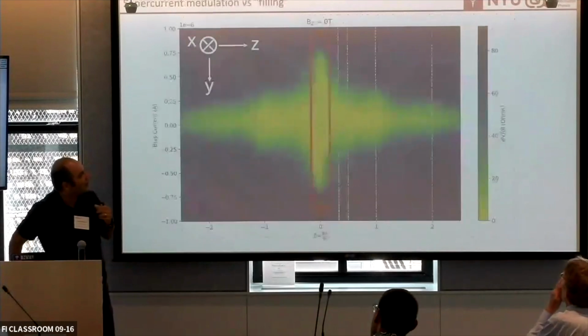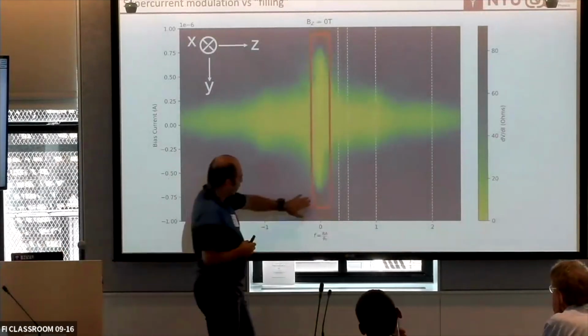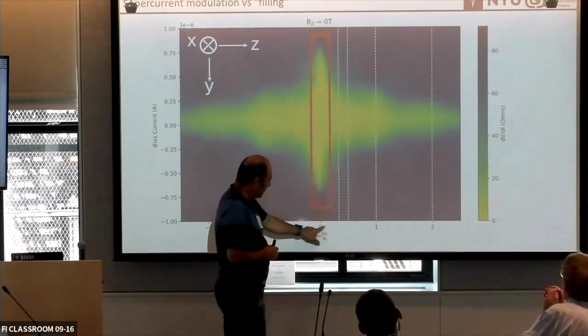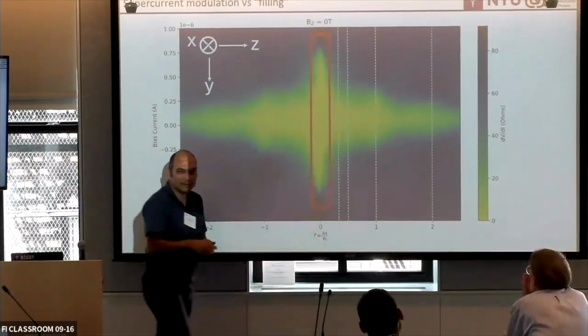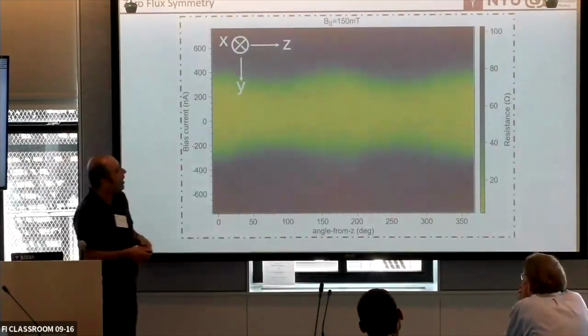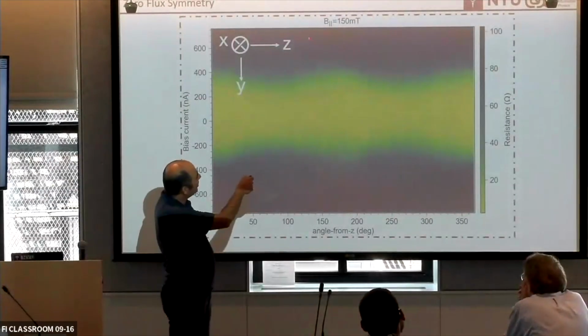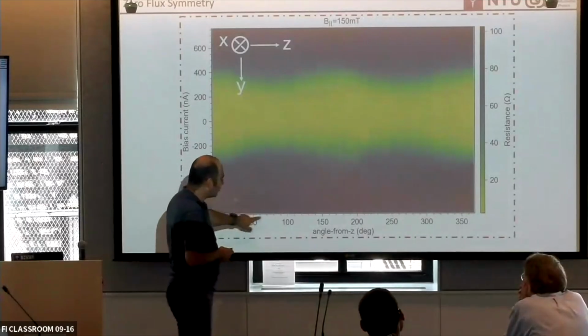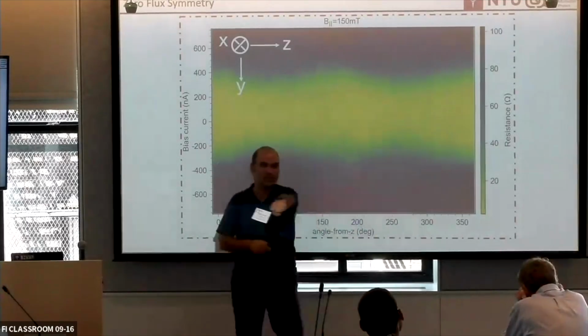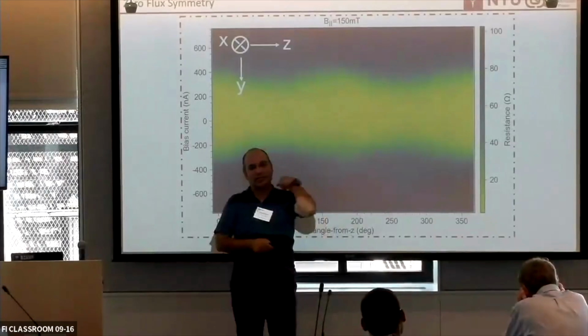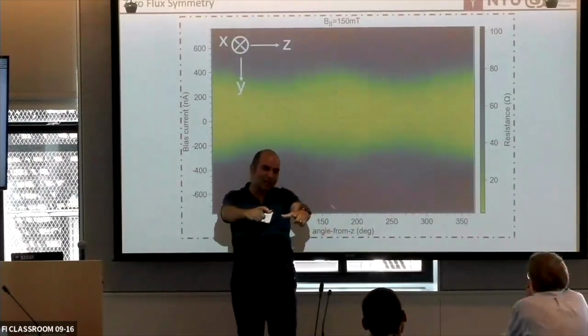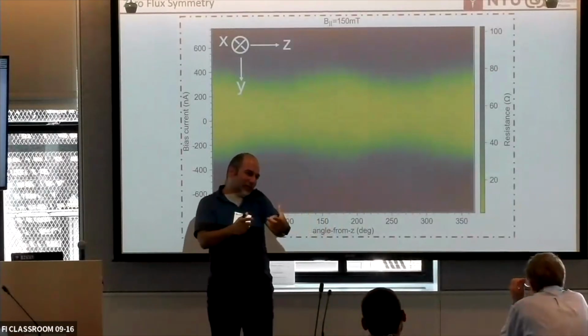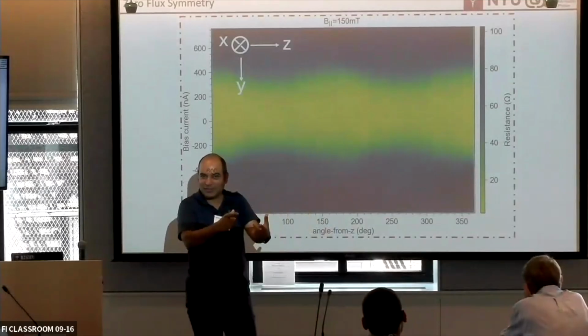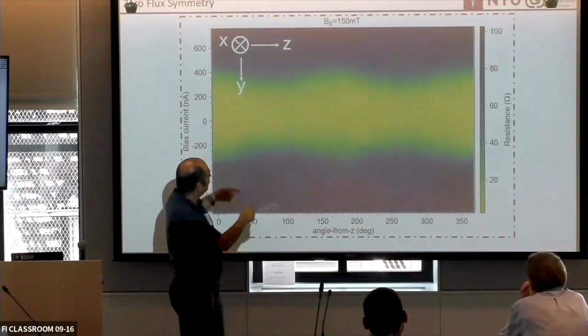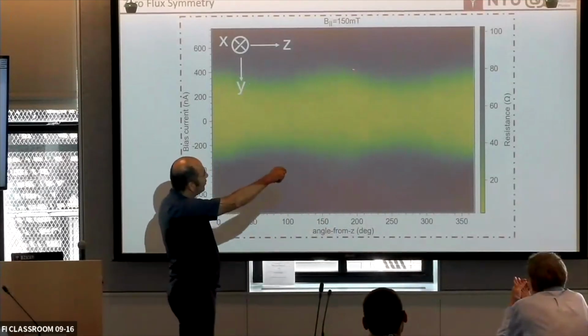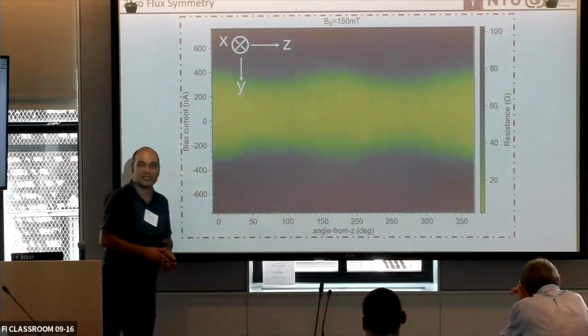This is the out-of-plane field, and I'm going to apply an in-plane field to my device. When I apply an in-plane field of 150 millitesla and rotate the angle, the lattice is a hexagonal lattice, so you would have thought there might be a 6-fold or 3-fold symmetry in the device. There is none. The resolution here is bad, but it's a 2-fold symmetry of the oscillation, right?